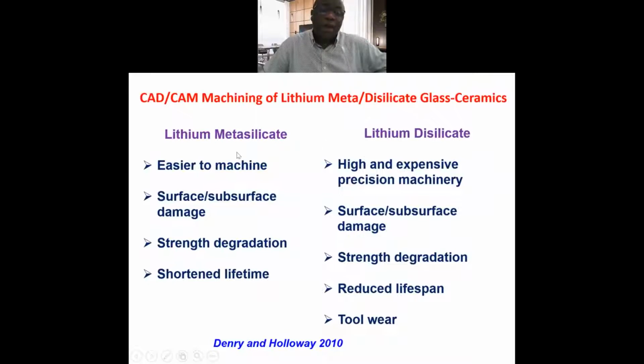cons of the two. When you process the dental restoration using lithium metasilicate, it is very easy to machine because it is very soft. Because of the softness and the low strength, there is a possibility of surface and subsurface damage, leading to strength degradation and shortened lifetime. Lithium disilicate can also be processed using high-precision, expensive machinery. It is very hard, so hard machining can lead to surface and subsurface damage, which can lead to strength degradation, reduced lifespan, and tool wear of the cutting tool.